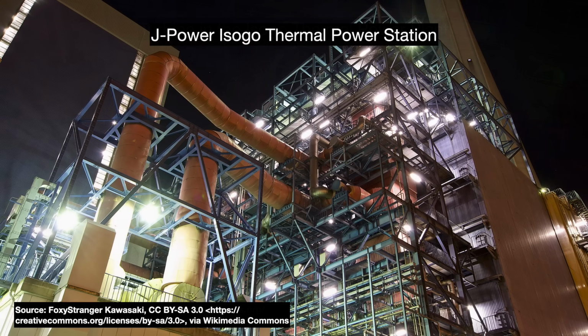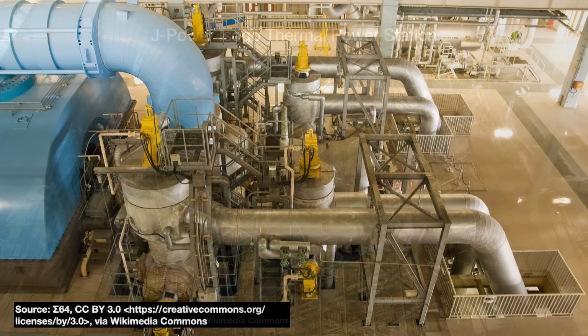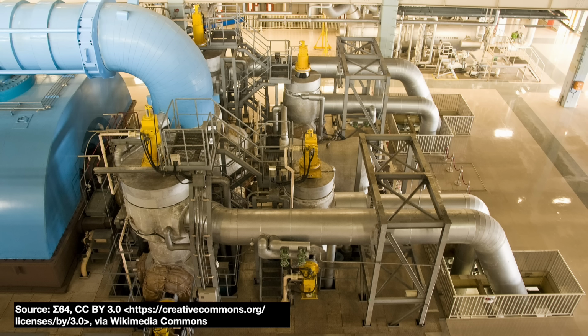Produced by Hitachi, the turbine operates at a wonderful 25 megapascals and 600 degrees Celsius. Notably, it adds 1 reheat cycle, raising the temperature to 620 degrees. The thermal efficiency was a record-breaking 45%.